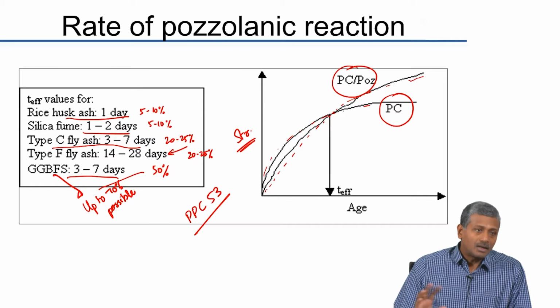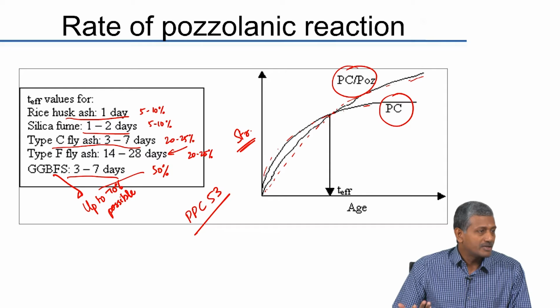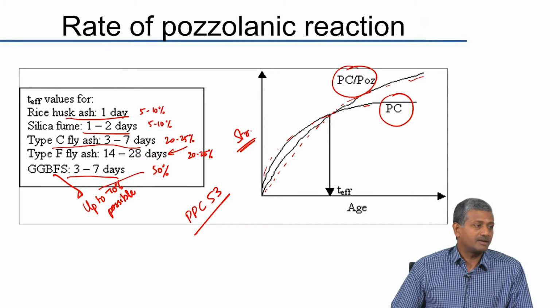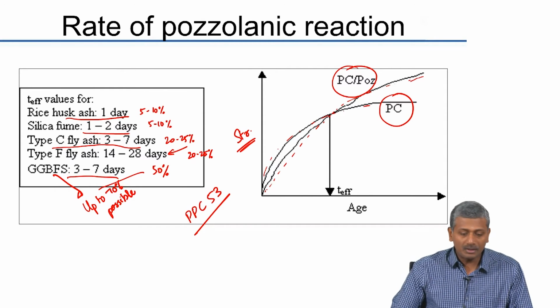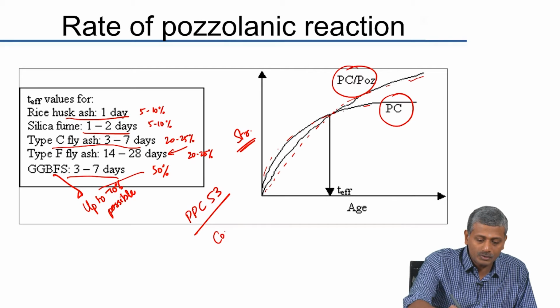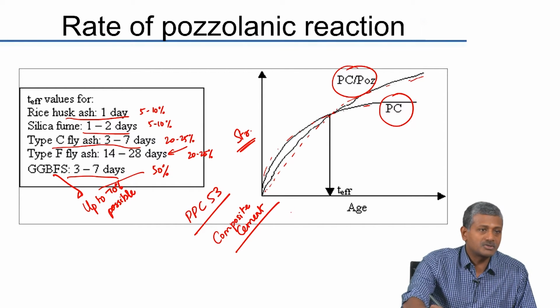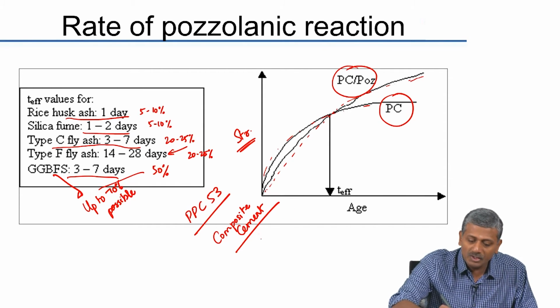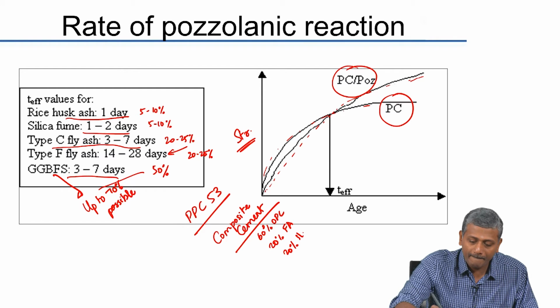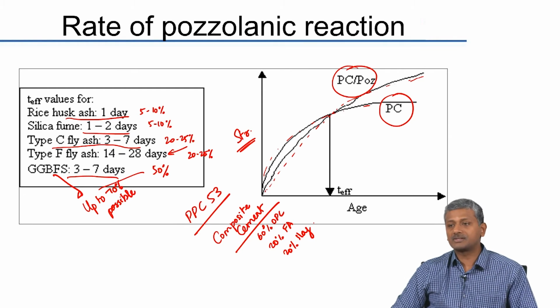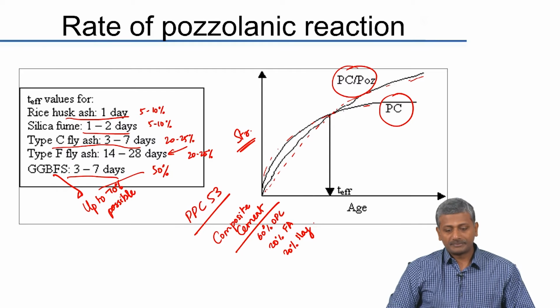Okay. The other condition is also there that sometimes when you are not able to use too much fly ash, what you can do is combine fly ash with slag and use that at a higher level of replacement. Today there is a new cement which has come up in Indian standards also, it is called composite cement. That is a new cement standard in India now, composite cement, I do not know the standard number. So, here we are essentially talking about 60% cement, about 20% fly ash and 20% slag. So, this is combining fly ash and slag in the formulation.